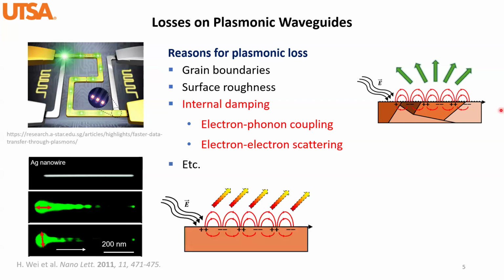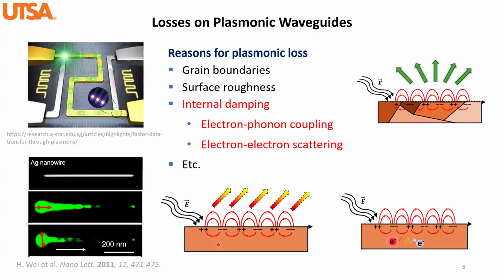And in terms of internal damping, we have two major categories. One is electron-phonon coupling. That is when the electron is excited by the external light to form a surface plasmon, and it travels and then meets the lattice vibration and gives its energy to the lattice vibration. That is what we call electron-phonon coupling. And then we have electron scattering, because there is a sea of free electrons in the metal, but not all the electrons are really excited by the light to generate surface plasmons. So there are what we call hot electrons and cold electrons. When hot electrons are oscillating and transporting the plasmonic vibration and then meet the cold electrons, they tend to give their energy to the cold electrons, of course.